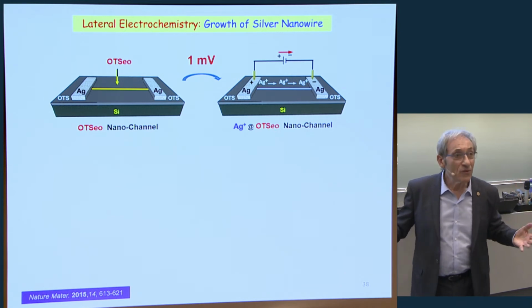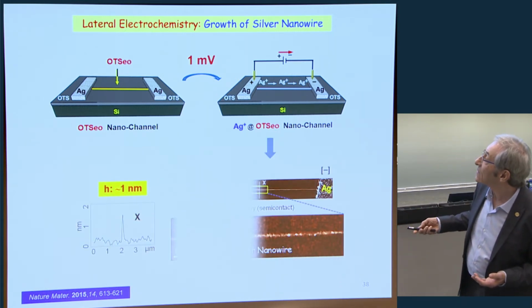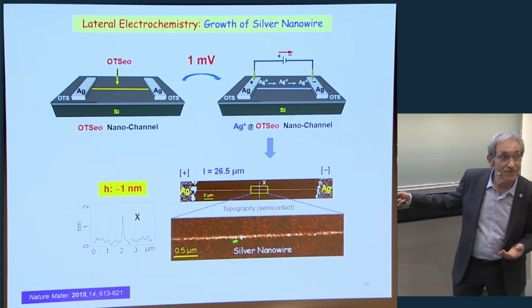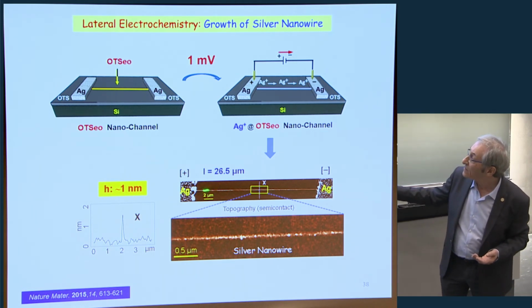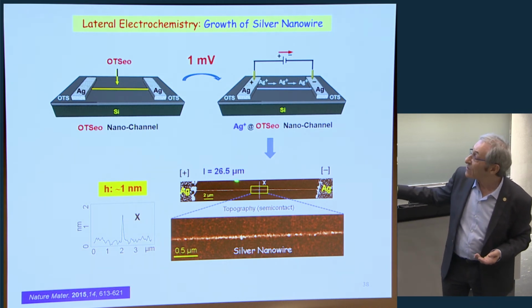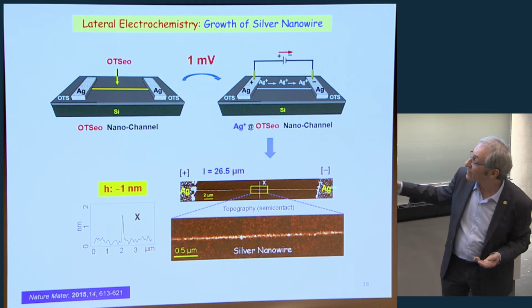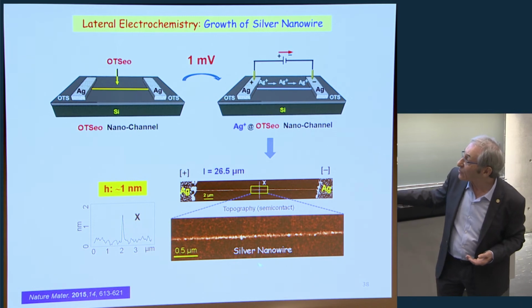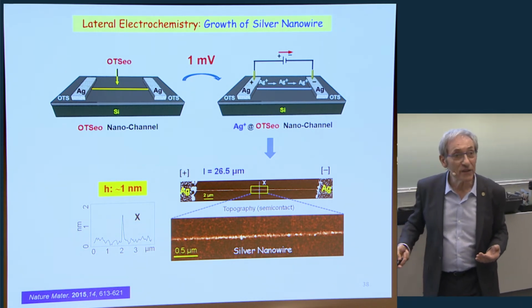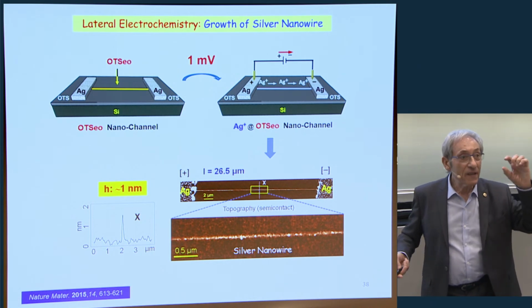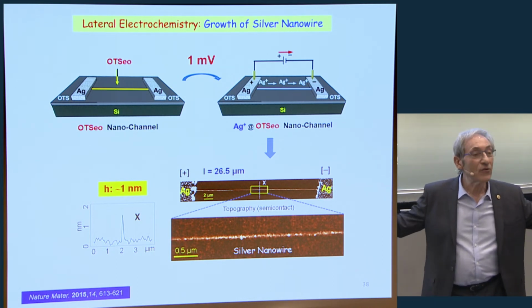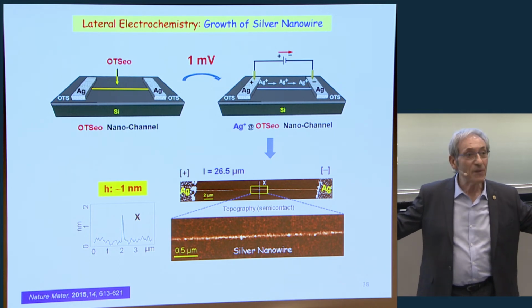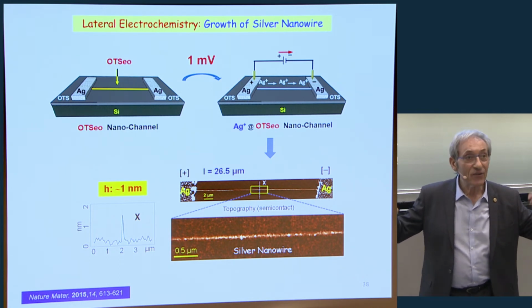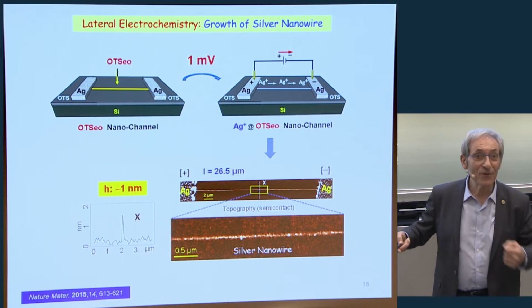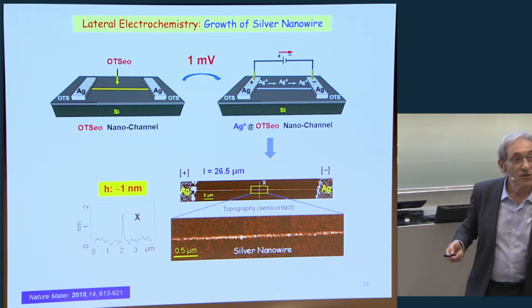The first is to look at AFM. So you see immediately that we have metal here. This is an AFM image, really an AFM image, of the length of this channel between these 2 electrodes. This is the cathode, the anode, and this is about 26.5 micrometers. And if you take a cross-section, you have something of the order of 1 nanometer of silver. And this is a limiting height. It doesn't grow. It doesn't matter how long you pass current, probably because when the electronic conduction takes over, no more ions accumulate and are reduced. So this is very important.